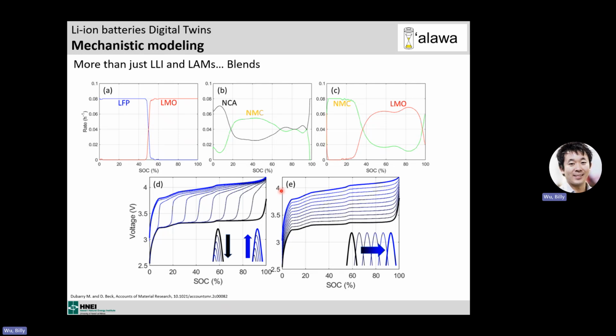But for the material nerds, does that happen as a solid solution or as a phase transformation? It's not the same thing. If it happens as a phase transformation, we have gradually one phase turning to the other. So if we take a completely hypothetical alchemic material turning from LFP to LMO, just for the example, it's not possible in real life, you can see that we start from the LFP plateau, and then when we increase the amount of LMO, we start to see more and more of the LMO plateau until we have only LMO.